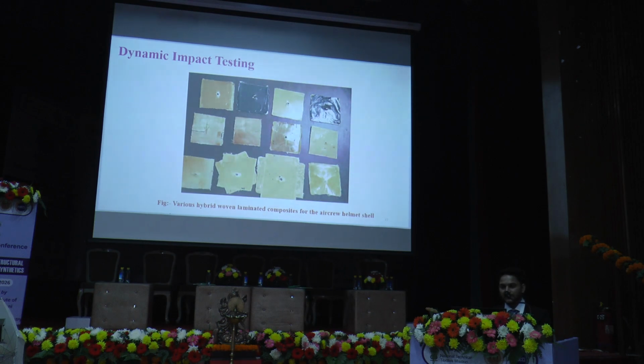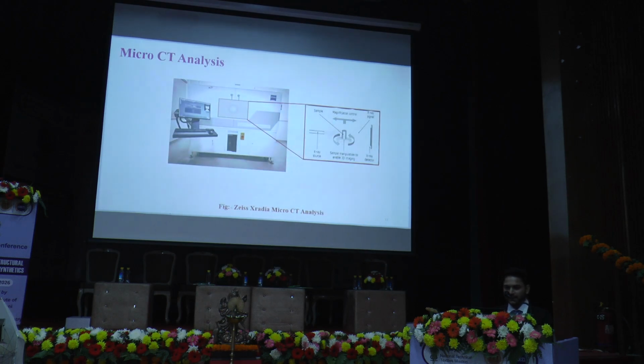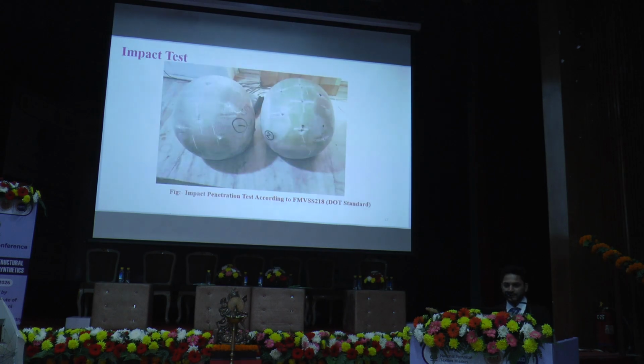So here, after the impact testing, we tried 12 samples with different stacking sequences, stacking laminates, utilizing different interlayer hybridization approaches. After that, we analyzed the damage morphology using microCT analysis. As you see here, this is the impact penetration test according to the Federal Motor Vehicle Safety Standard 218 DOT standard.